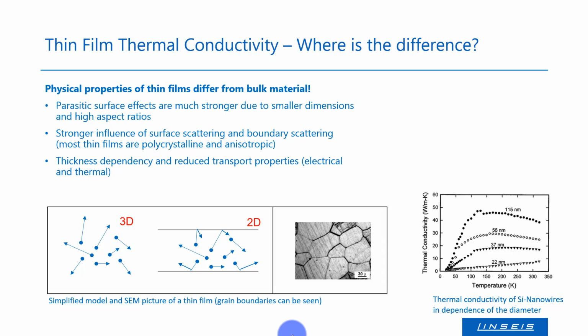The physical properties of thin films are different from bulk material because the parasitic surface effects are much stronger due to the smaller dimensions and high aspect ratios. That means the surface parts play a much bigger role than in bulk material. The weight of this influence depends on the volume to surface ratio and is thus thickness dependent.